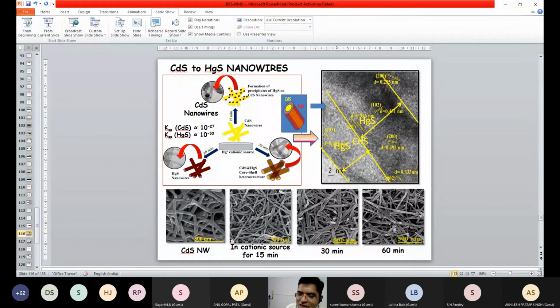So the outer part is HgS and the inner part is CdS, right? Here you can see HgS as well, because it covers the whole surface area. But if you look inside, it is CdS, and just outside it is only HgS. We took this CdS in the mercury source for different time intervals: 15 minutes, 30 minutes, and 60 minutes. Depending upon the time interval, we can alter the thickness of the shell on the CdS core. So the thickness of the HgS is possible to control. That is the beauty of solution chemistry.